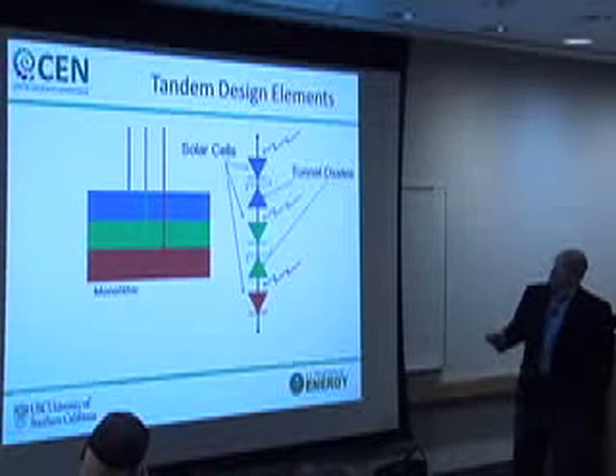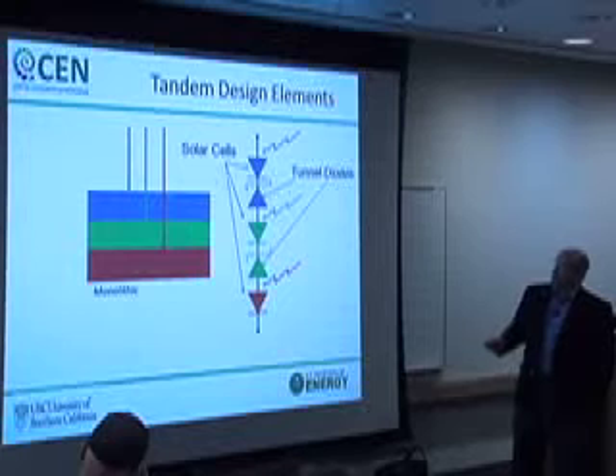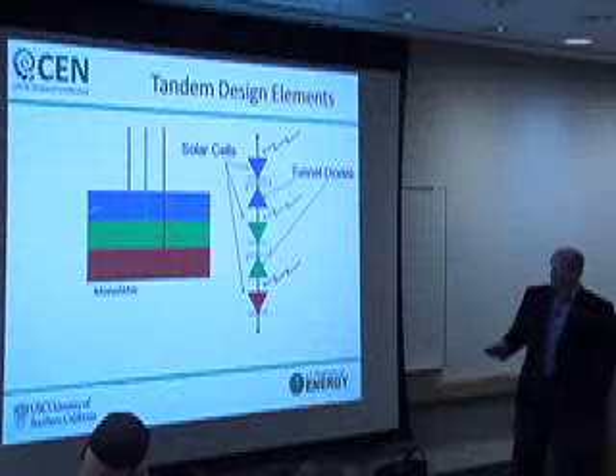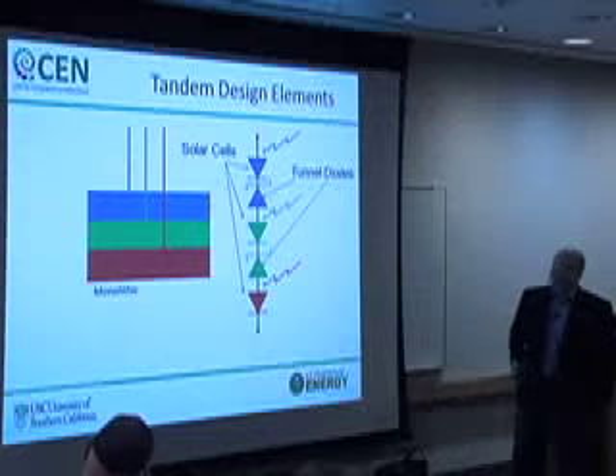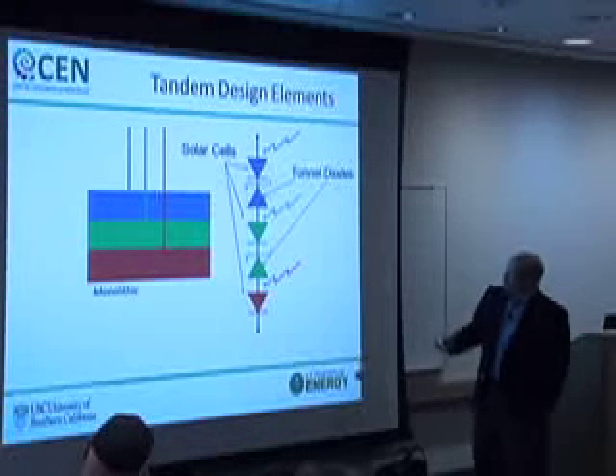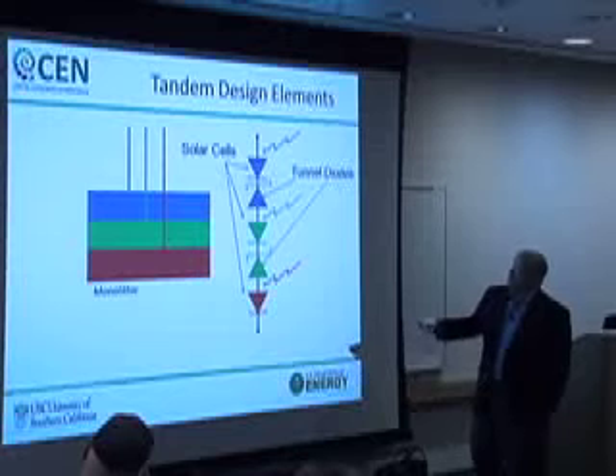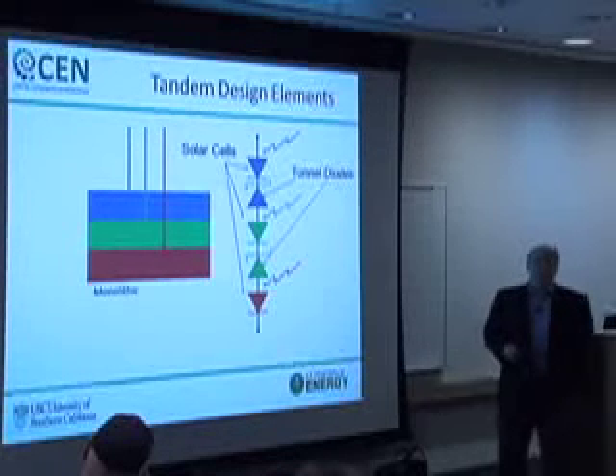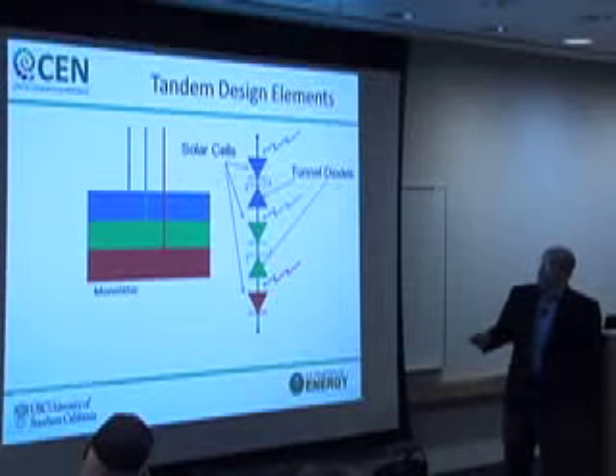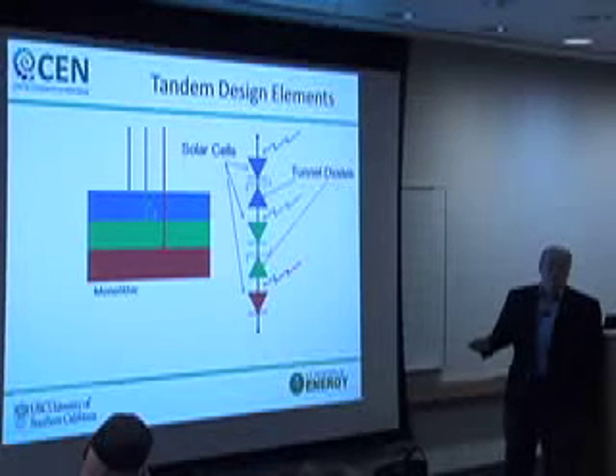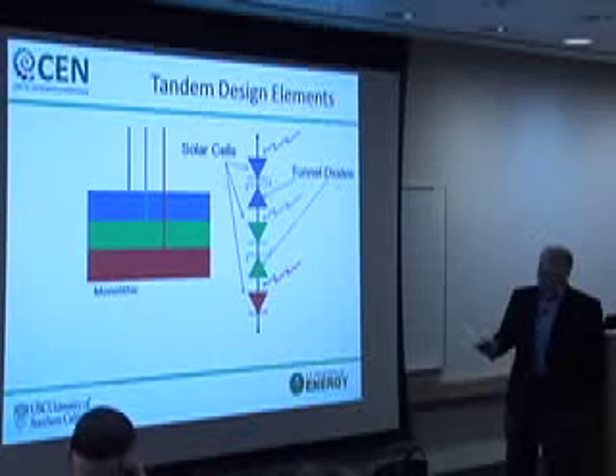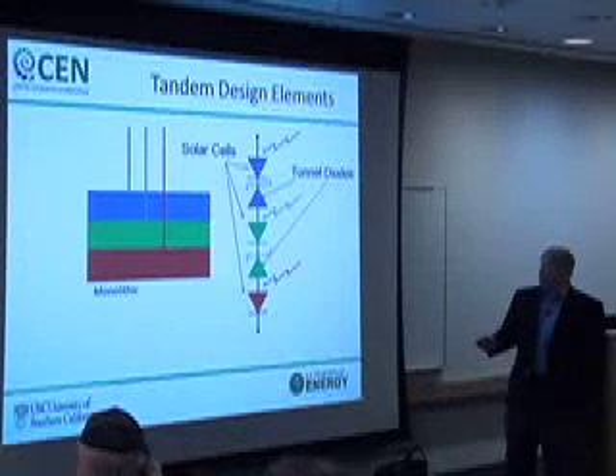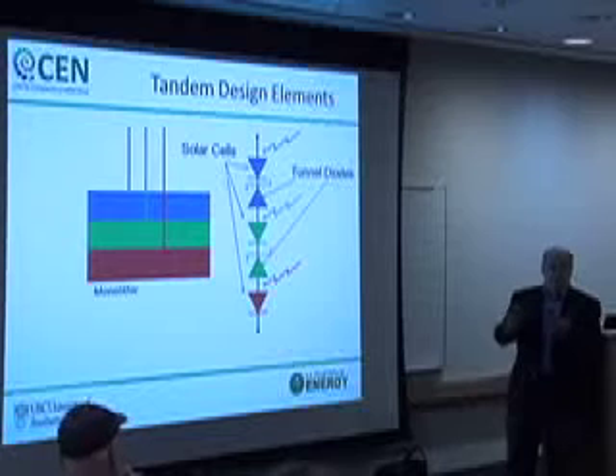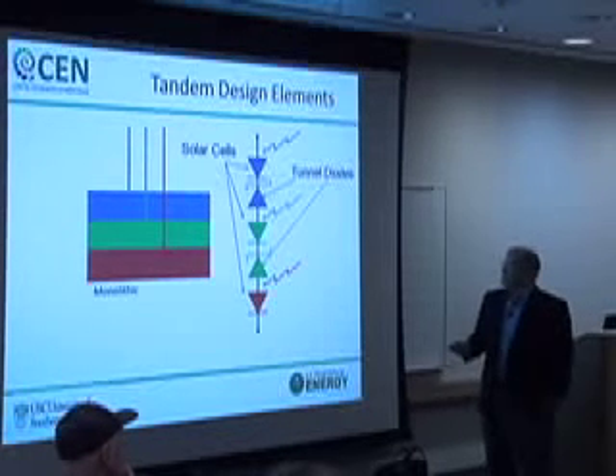So in order to make a successful solar cell of this sort, you have to make good, efficient solar cells out of 3 or more types of materials, and then develop the interconnect technology to be able to electrically connect them so that you add up the voltages from all 3 cells. The other part of the trick here is that you need to match the currents from each of the cells. So the absorption properties, the absorption threshold, the thickness of the layers and whatnot all have to be carefully tuned in order to match those currents.